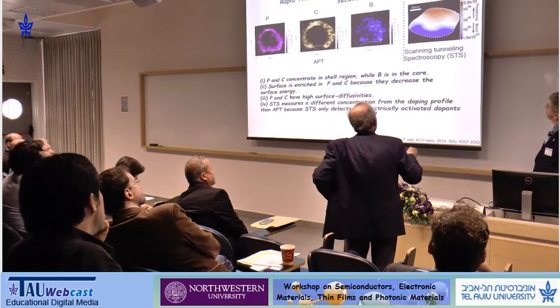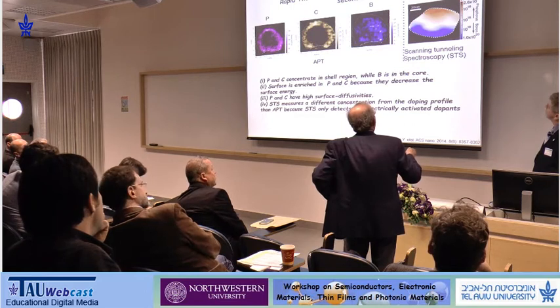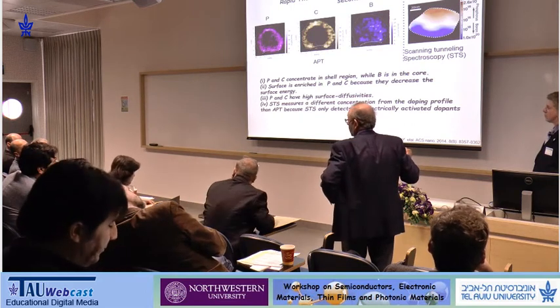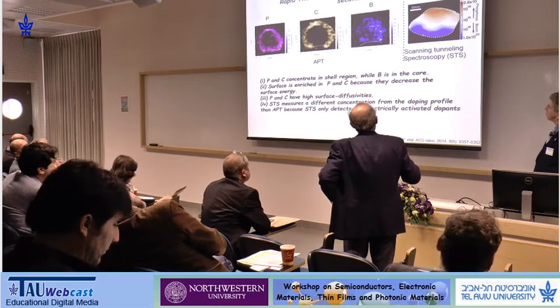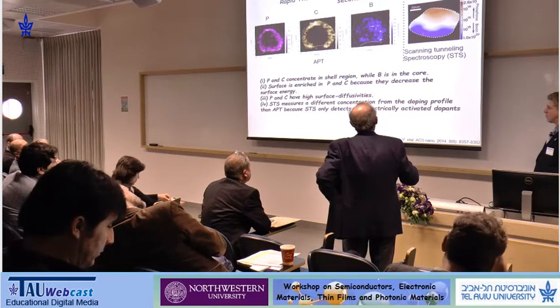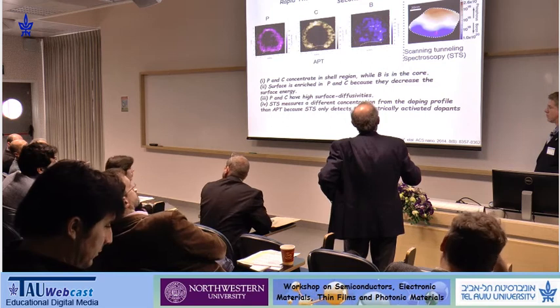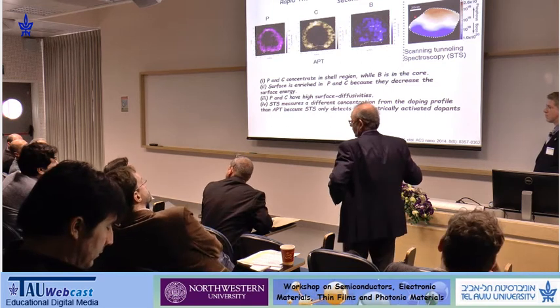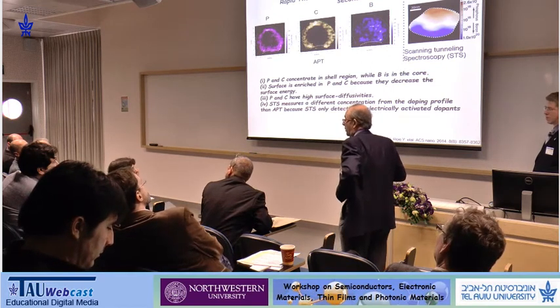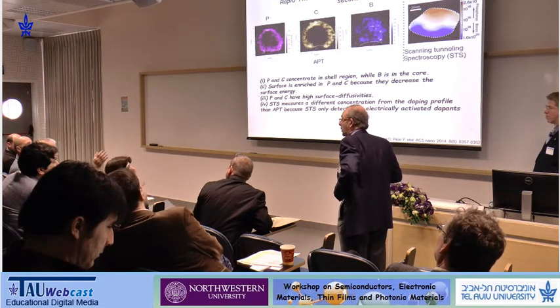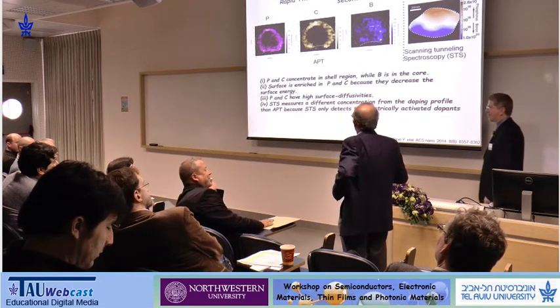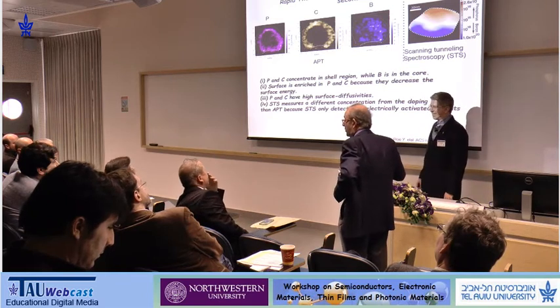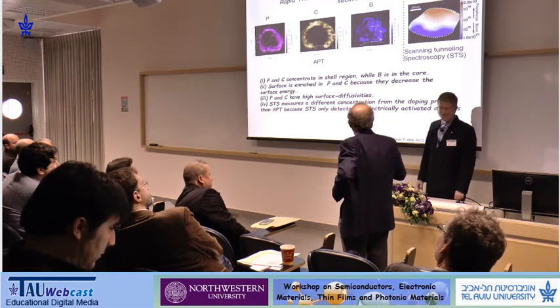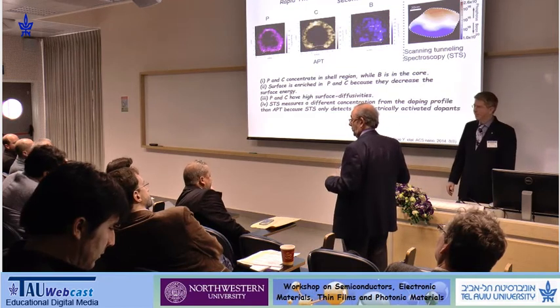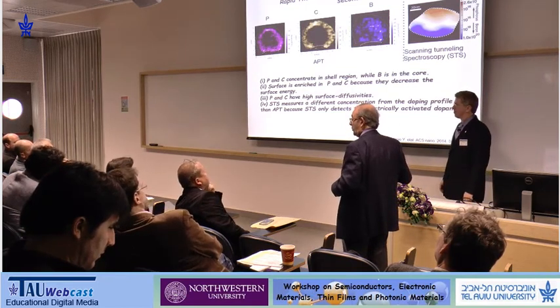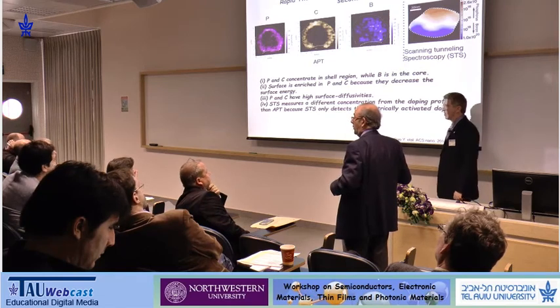And then there's a scale on the side here, which gives you the concentrations in number per cubic centimeter. And these are the electrically active elements, right? Electrically active boron, electrically active phosphorus. Whereas these include both electrically active and electrically inactive. So the atom probe gives us the total amount, whereas the STS only gives you the electrically active component. I'm just interested in the geometrical setup.